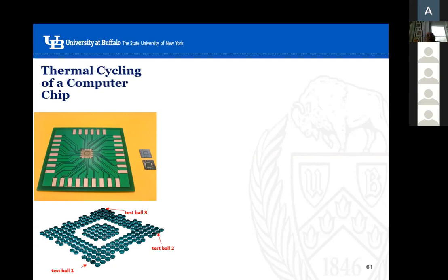If you do really detailed modeling, ultimately each hysteresis loop will say how much energy you are losing, how much energy is absorbed. So there's a limit. We assume in the Coffin-Manson relation, even if you do cumulative damage, ultimately we can derive it is equivalent to the sum of the hysteresis energy, cycle by cycle, stable cycle, what is the energy associated with each hysteresis loop.